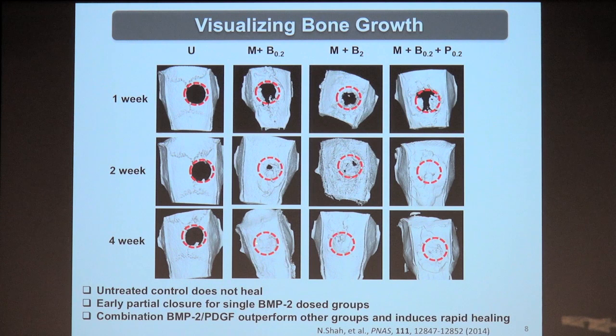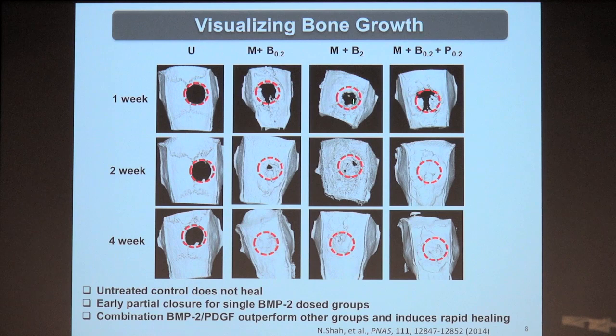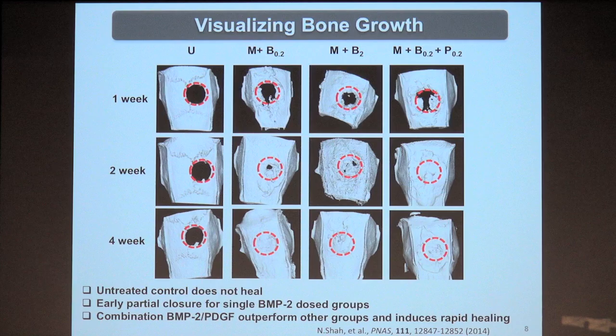We can see that if we increase the dose to 2 micrograms, then we end up with the same rate. So we don't need to increase dose. We can stay at these low doses. And as you remember, low dose is what we want. In fact, the levels that are introduced in the FDA-approved product are in the milligrams. Here we're working three orders of magnitude or four orders of magnitude lower than that.